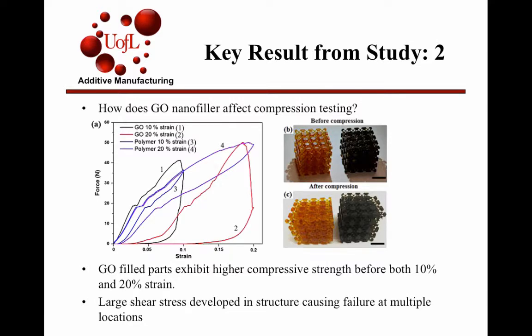And then this is one more. They did some compression testing. For these, they actually printed a structure. As you can see here, this is the one with the polymer without the graphene oxide and with the graphene oxide. There was also an example in my first slide of a structure that was printed with both. For compression testing, they saw that the graphene oxide filled resin can accept more force, with more strain. What they did see also was some limits to the structure, and in fact, both of these structures failed, right around the end of their strain curve, and broke into like 5 pieces.